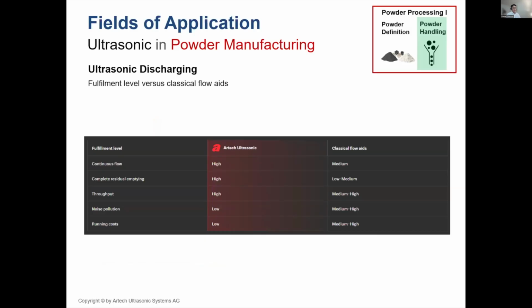So compared to classical flow aids, the benefits are obvious. So continuous flow, almost completely residual emptying compared to mechanical knockers, for example. A high throughput rate, almost no noise because we work in a frequency of 30-38 kilohertz, almost not hearable. And the running costs are really low because the downtime can be reduced, and also the energy consumption is very low.